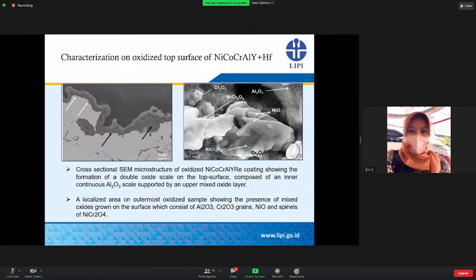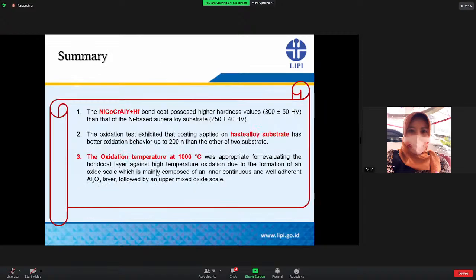I will summarize the result as follows. Nickel, cobalt, chromium, aluminum, yttrium, and addition of hafnium in the bond coat having a high hardness value. In the oxidation test, the coating applied on hastelloy substrate has better oxidation behavior, and the oxidation temperature of 1000 degrees C was appropriate for evaluating the bond coat layer against